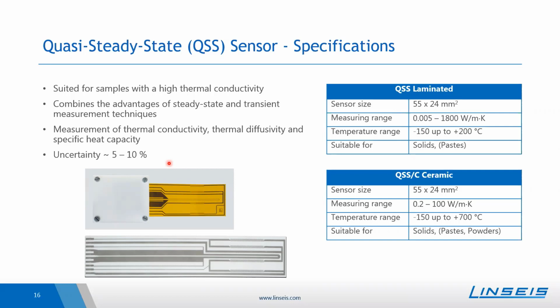Yes, so as mentioned, it's for the high conductive samples. Because of the different layout, it is able to go to higher thermal conductivities compared to the THB sensor. So here also the measurement times are slightly higher compared to the THB sensor for the same thermal conductivity range, as it needs to wait until there's a quasi-steady state.